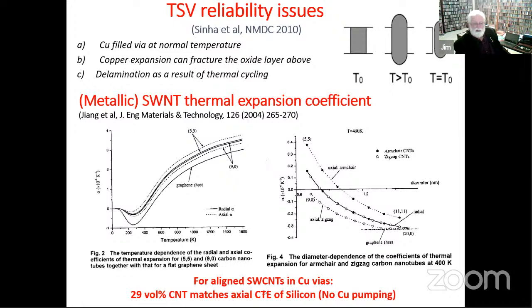But the thing is that if you mix carbon nanotubes in copper, you can reduce the coefficient of thermal expansion. And in fact, in a study of ours, if you had aligned single wall carbon nanotubes in a copper via, so they're all running in one direction, a 29% volume carbon nanotube content will exactly match the coefficient of thermal expansion of silicon. So there's no pumping. And also the axial and radial values are slightly different, but you can also get much less pressure on the silicon wafer with the carbon nanotubes in the copper rather than just bare copper.